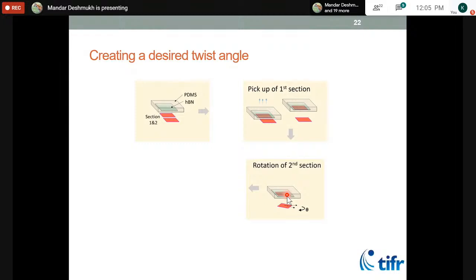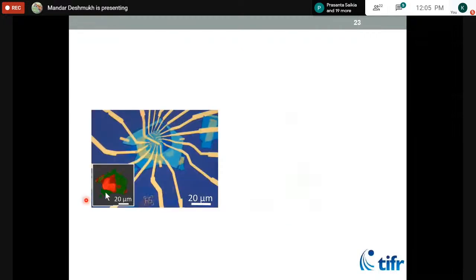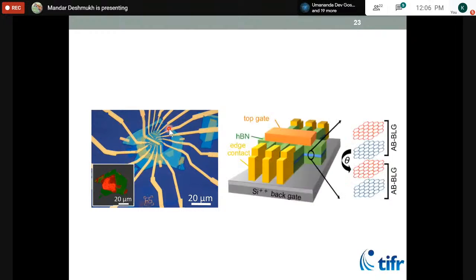And then these two layers are now rotated by a precise angle. Then you bring them in contact and you pick up this layer. These graphene layers like to stick to each other preferentially. So now you have realized a layer of two which has a precise rotation angle between them. And then you can make some complex devices. This is much more complex than the earlier device that I showed you. This is a scale bar, 20 micrometers, about 1/5 of human hair diameter. And these are all electrical connections for doing electronic measurements.